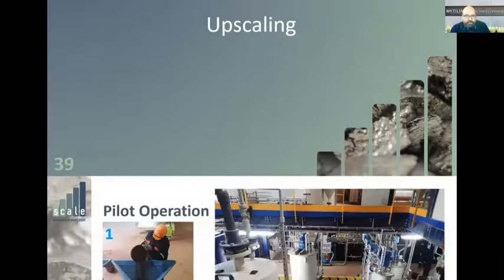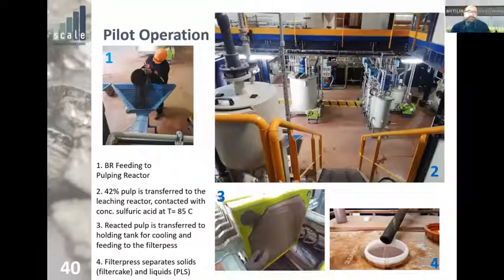So that was the lab results, but we set out to do the upscaling to see if this actually works. And so this is our leaching pilot at Efthymios in Greece. It has several reactors. Basically, we feed bauxite residue into a pulping reactor. The bauxite residue goes in a pulp of 42% into the leaching reactor, where it's contacted with concentrated sulfuric acid at 85 degrees. And after a retention time, it goes to a holding tank, and from there to the filter press, where we separate solids and liquids.